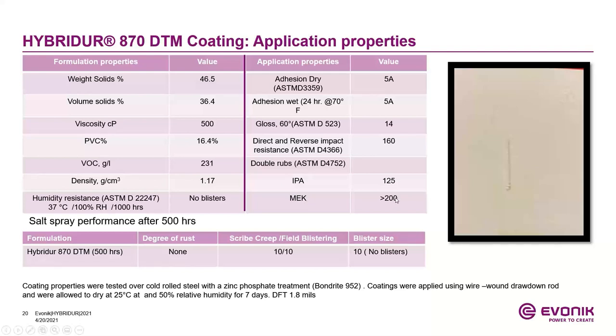So for these properties, the coatings were applied again on cold rolled steel with a zinc phosphate treatment, Bonderite 952. And in this case, these are spray applications, sprayed for the corrosion resistance as well as the humidity resistance. And they were dried, and the dry film thickness here is about 1.8 mils. So Hybridur does offer outstanding corrosion protection, and they can be used for direct metal coating formulations.